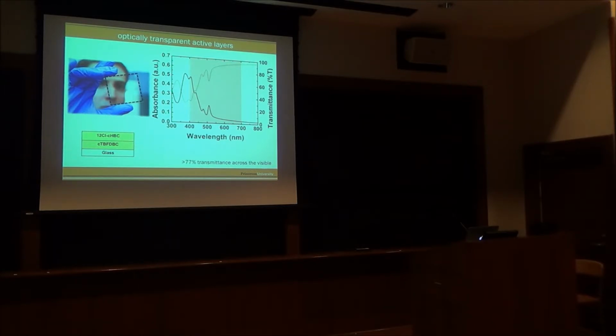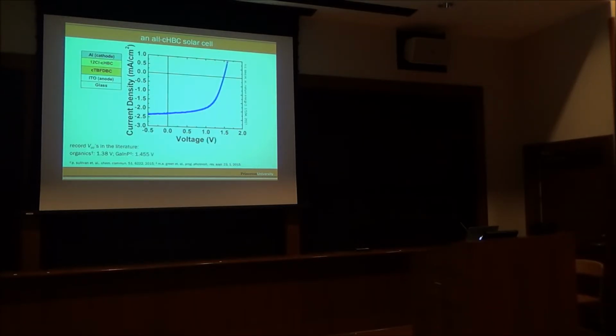But of course, this is only the thin films. We can make devices. Again, we have our two electrodes, the donor and the acceptor. That's our current density as a function of voltage profile. You can see immediately that the open circuit voltage is actually quite high, and that's because we've gone to wide bandgap materials. With wide bandgap materials, you're getting a big open circuit voltage.